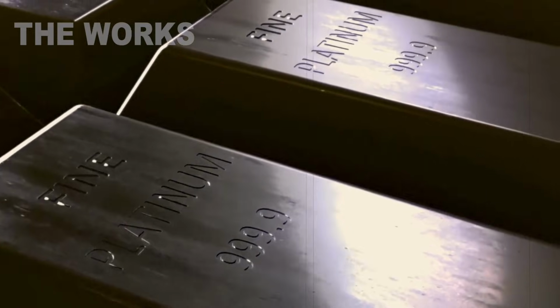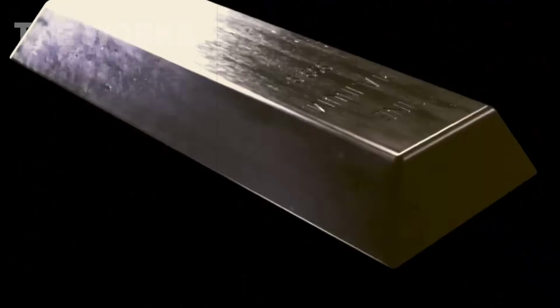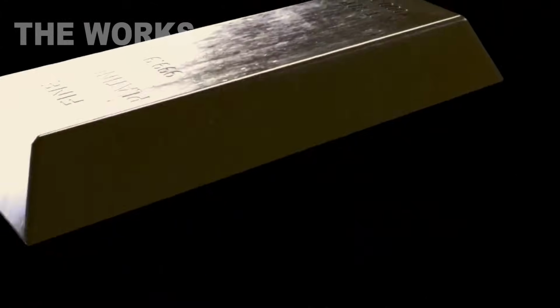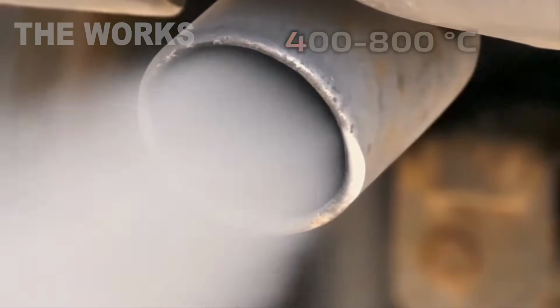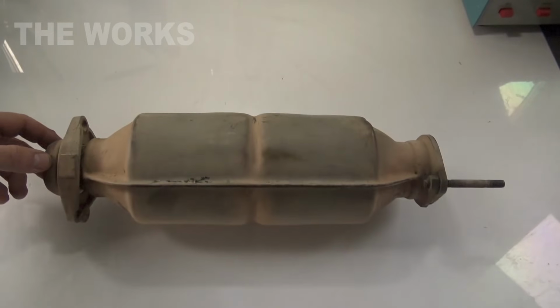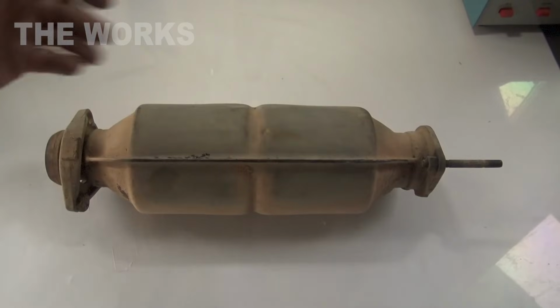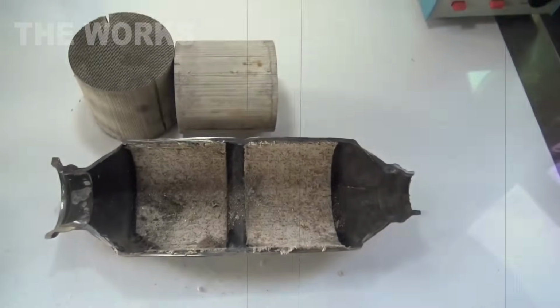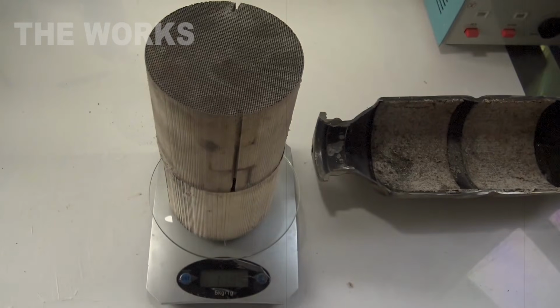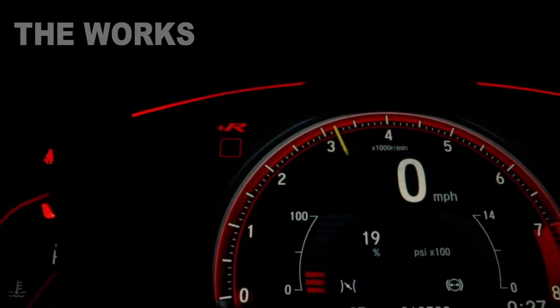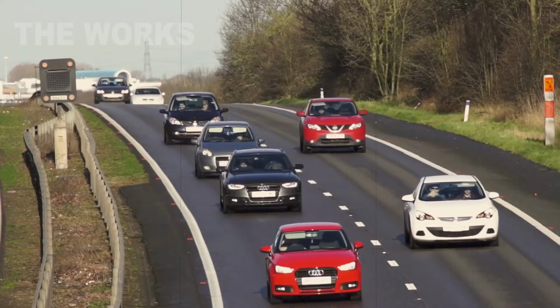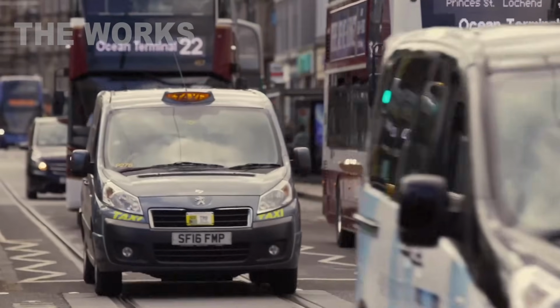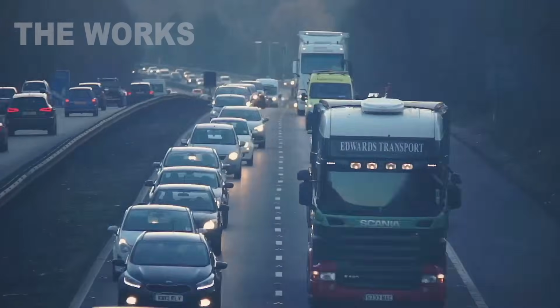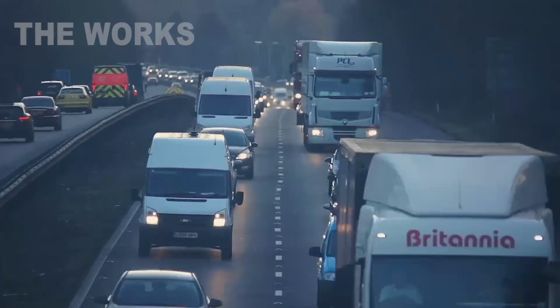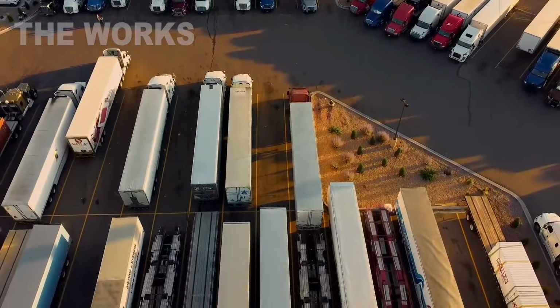Palladium and platinum oxidize carbon monoxide and hydrocarbons into carbon dioxide and water. Rhodium reduces nitrogen oxides back to nitrogen. Exhaust gases at temperatures between 750 and 1470 degrees Fahrenheit flow through the honeycomb. Reactions happen on the metal surfaces. What comes out? Almost pure nitrogen, carbon dioxide, and water vapor. Efficiency? Up to 98%. Without a catalytic converter, a car dumps dozens of grams of toxins into the atmosphere every mile. With one, fractions of a gram.